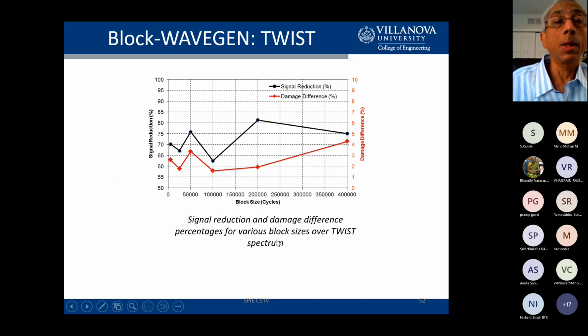And this kind of shows us some more results. We use what's called a blocking technique, and so we developed an algorithm called block wave gen. For the twist spectrum, we've found that depending on the size of the block, you can achieve various amounts of reduction. That's the dark line. And in terms of the damage difference, we want to keep it less than 5%. We find that we can keep it less than 5% for each of these different chosen block sizes.